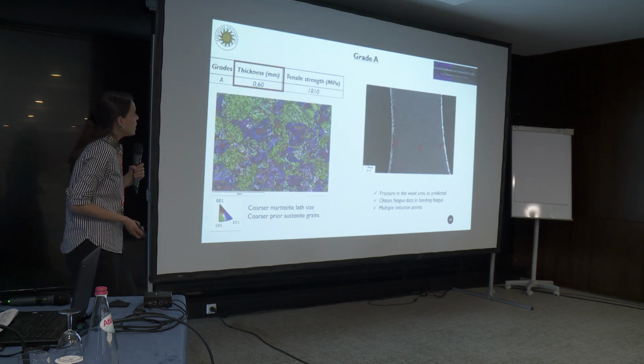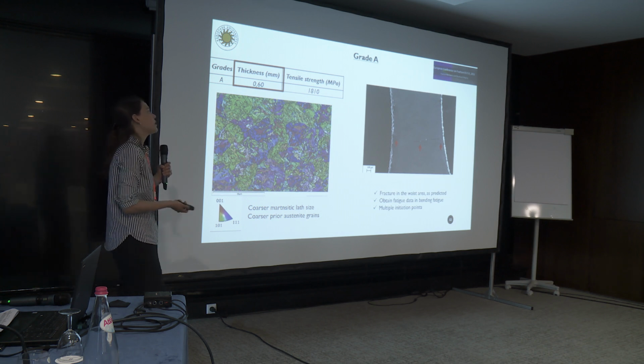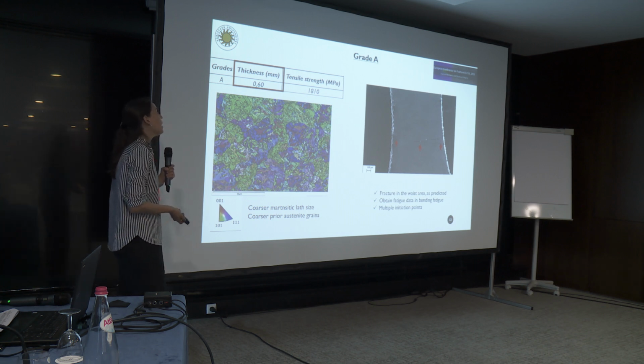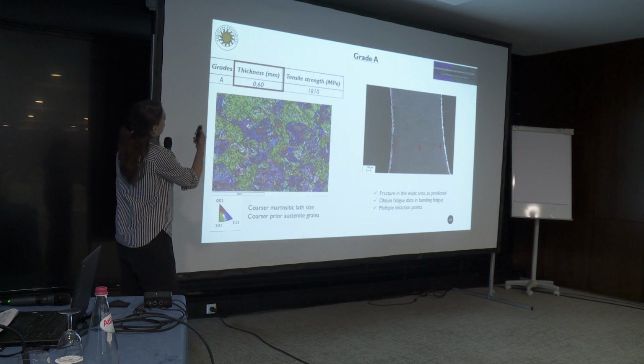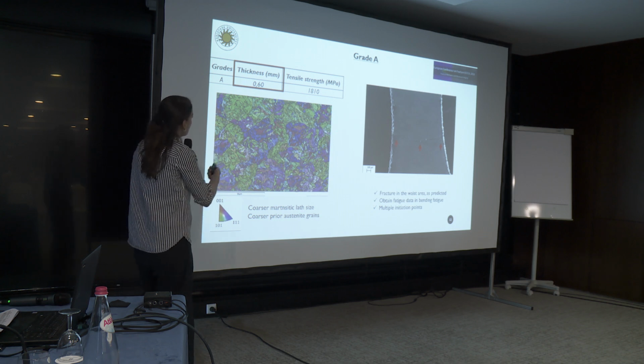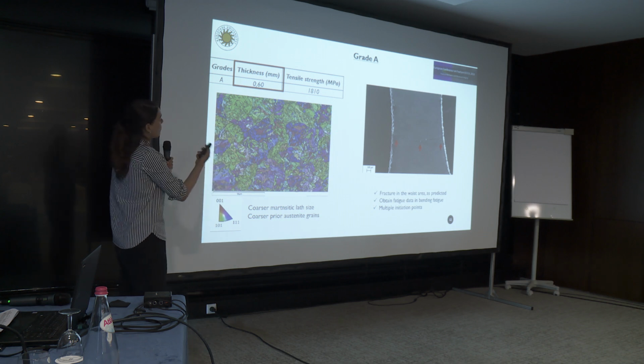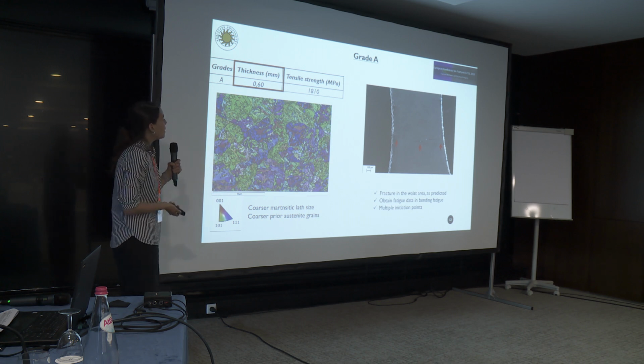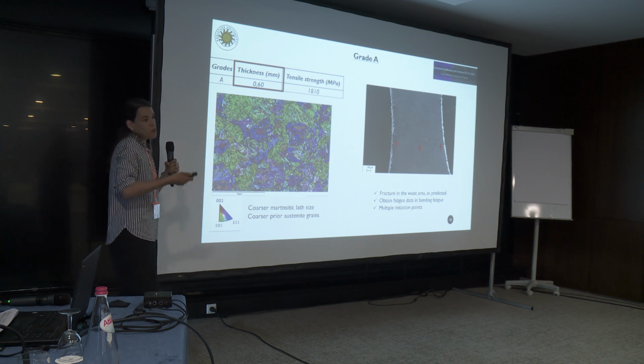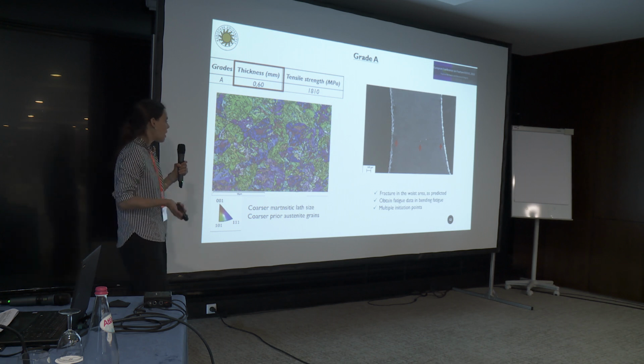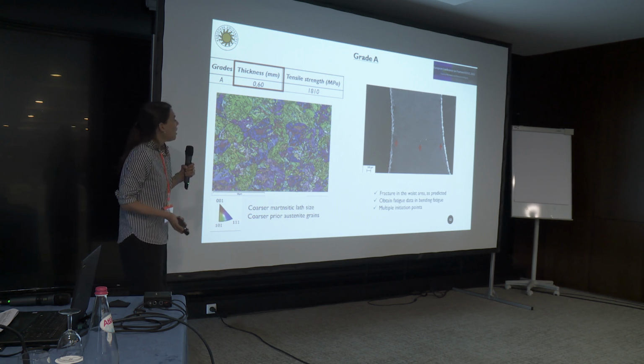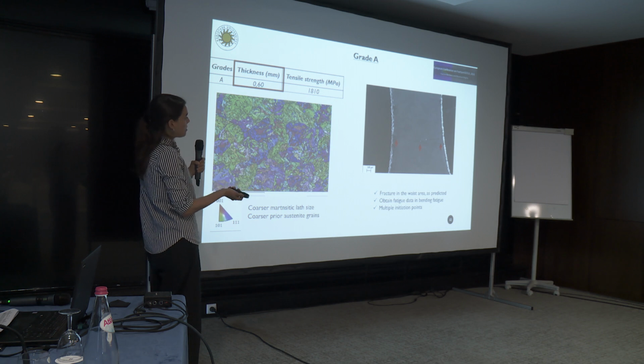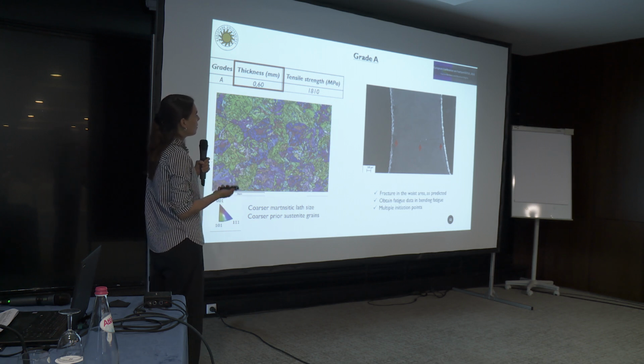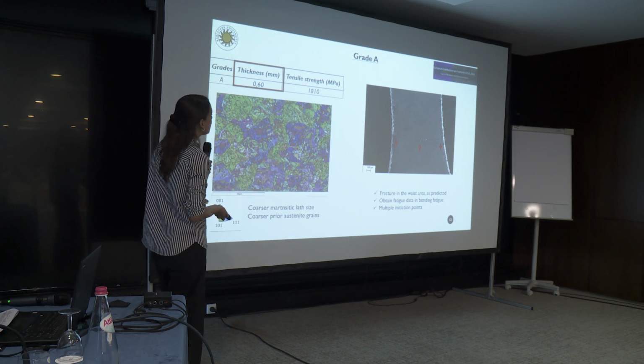And last but not least, we have grade A. It is of different thickness than the other three, a thickness of 0.6 millimeter. EBSD analysis gives us the image that the prior austenite grains are bigger and the martensitic grain structure is bigger in that case, and it's okay because it's thicker. We tested this thickness and we have fatigue data for that as well.